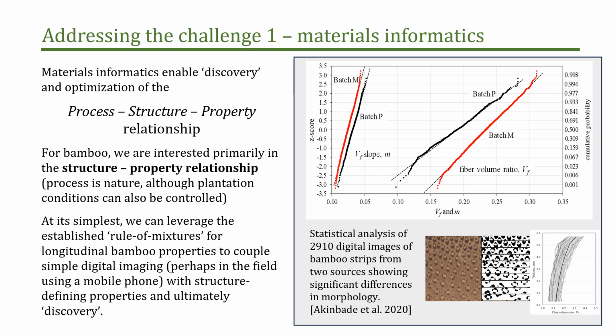And so what we're showing on the right-hand side of this slide very simply are the results of about 3,000 digital images of bamboo strips. These were reportedly essentially the same source, and were being used in engineered bamboo in the same manner. The engineered bamboo had the same, or allegedly the same, material properties, and yet it was very clear when we looked at the feedstock, the bamboo strips, we had two very distinctly different batches involved in this particular data, and that's seen in the statistical data above. And material informatics allows us to see that very, very quickly.